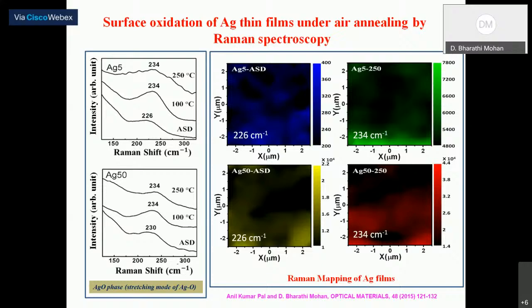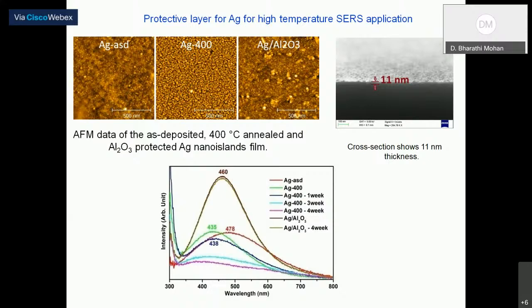So how to avoid this oxidation of silver film? What we have done is we made a protective layer on top of silver and tried to look at the oxidation of the silver film. Initially we prepared a thin film of silver with 11 nanometer thickness, and the thickness is measured from the cross-sectional image using FESEM. And then the same film is annealed at 400 degrees Celsius, and you can see a homogeneity in the particle size and shape. After this, we coated this film with Al2O3. The thickness of the Al2O3 ranges from 3 to 5 nanometer.